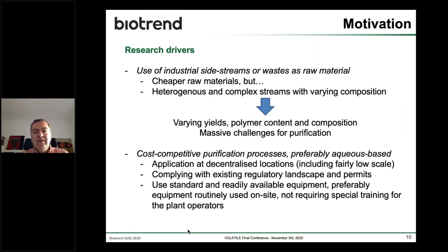for the raw materials. And typically, these side streams have a much lower cost than the refined raw materials. However, that comes at a price, which is the variability and the complexity of these streams with varying composition. And this, of course, needs to be taken into consideration when the process is being designed. And the other pressure point, as I mentioned, is the purification process. So preferably aqueous-based. It's very easy to purify these compounds using solvents, but that's something that is really being phased out from the industry.